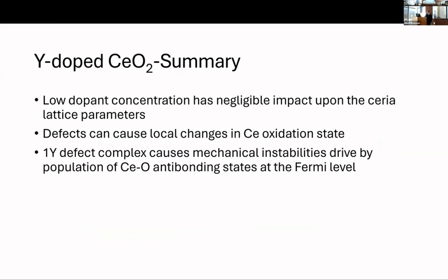So just as a summary of yttrium dopants, low dopant concentration, as we expect, has negligible impact upon the ceria lattice parameter. And we saw in the 1Y reaction that we can see local changes in the cerium oxidation state. And then we were able to prove that the 1Y defect complex caused the mechanical instability in 1Y, driven by the population of the anti-bonding states at the Fermi level.